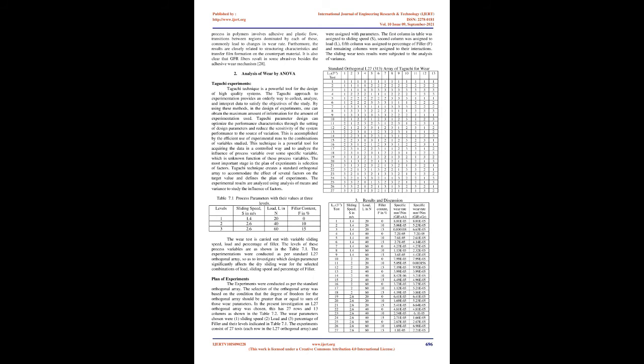The experimental results are analyzed using analysis of means and variance to study the influence of factors. The wear test is carried out with variable sliding speed, load, and percentage of filler. The levels of these process variables are as shown in Table 7.1. The experiments were conducted as per the standard L27 orthogonal array, so as to investigate which design parameter significantly affects the dry sliding wear for the selected combinations of load, sliding speed, and percentage of filler.